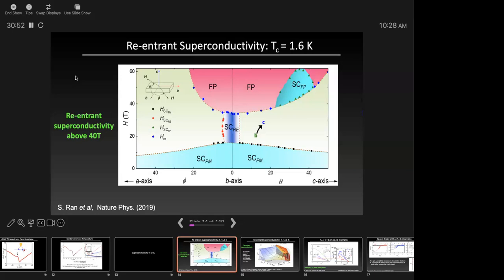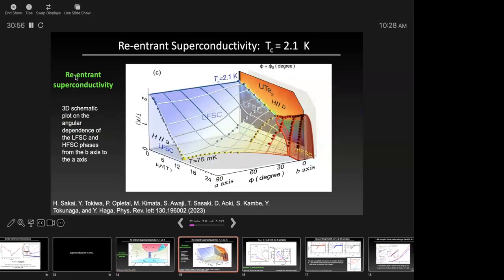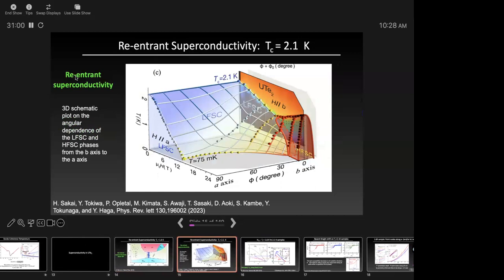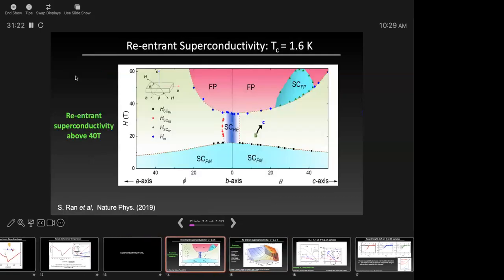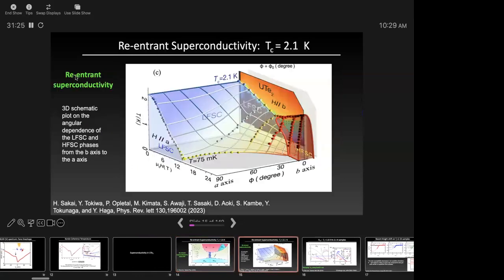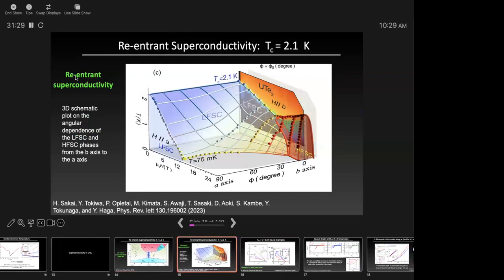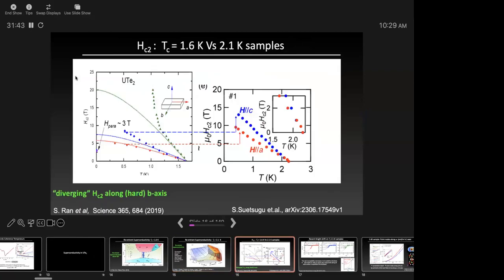The first thing is, let's just call this a high TC sample. In this high TC sample, you see the same reentrant superconductivity. This looks complicated, it's not actually. This is nice because along this axis you can see the transition temperature. This surface is H parallel to A, this surface is H parallel to B. And if you look here, this is the direction where you have the reentrant superconductivity, and that's exactly what happens. So as you increase field, you get this new superconducting region, even in this new sample. Okay, so in that sense, these two samples are quite similar. The TC is not that different. It's between 1.6 and 2.1 Kelvin.